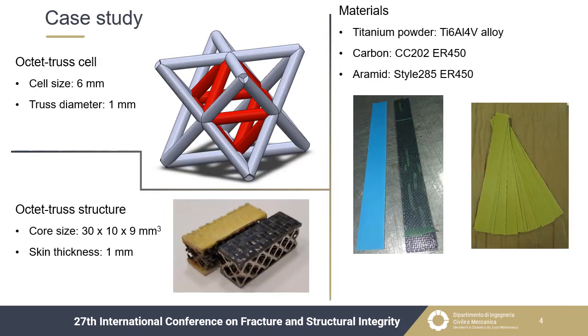The characteristics of the lattice core are very important since they influence the mechanical peculiarities of the whole structure. As concerns the cell type, the octet truss lattice was chosen. This cell is a face centered cubic cell formed by 24 beams, with an octahedron inside, formed by 12 beams. The cell side was chosen equal to 6 mm, while the beam diameter to 1 mm.